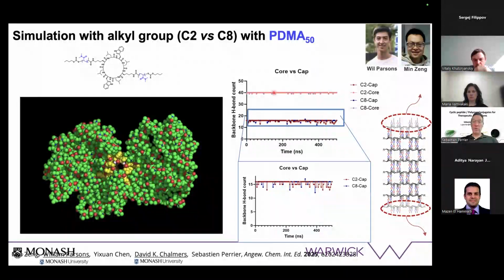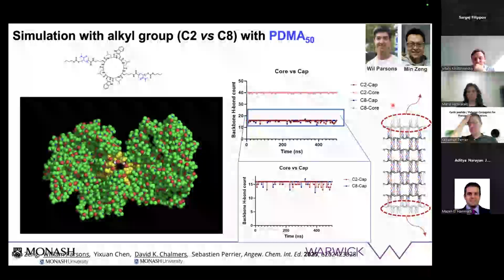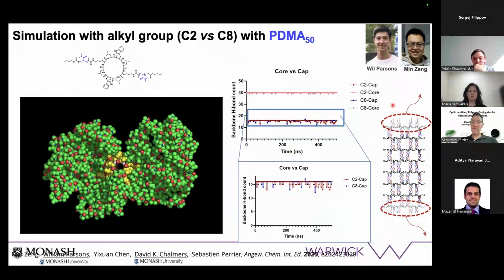And what that's telling us is that the tubular structure, when it's breaking down, because it is a supramolecular assembly and the peptides are breaking away from each other, it will be preferentially from the end of the tube rather than from the middle. So the tubes don't break in two or three or four as they fall apart. They actually shave off their end groups one after the other. And this is quite critical for the application in drug delivery that we're going to discuss.